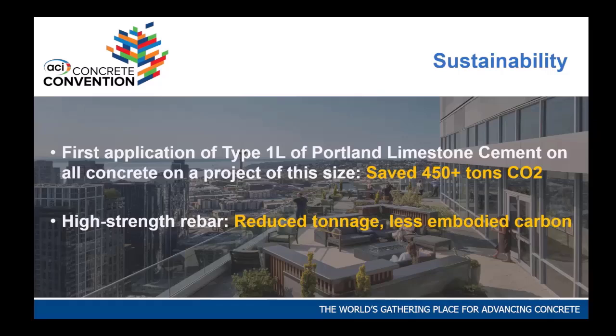So that was a big thing, and high-strength bars also reduce the embodied carbon. Now, depending on how steel is being made, either from iron ore or recycled steel, most of the steel we use in the Northwest is recycled, so there isn't a lot of CO2, but there's still some, because you have to heat it, melt it, and transport it. So by using high-strength steel, you reduce the amount of rebar you use, and therefore that helps with the carbon footprint.